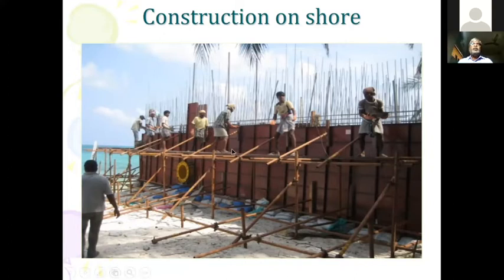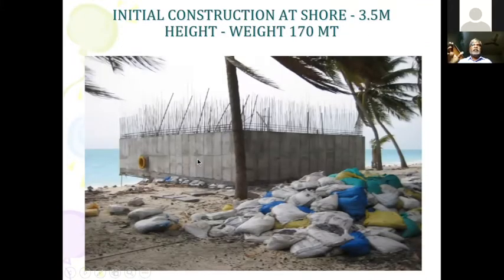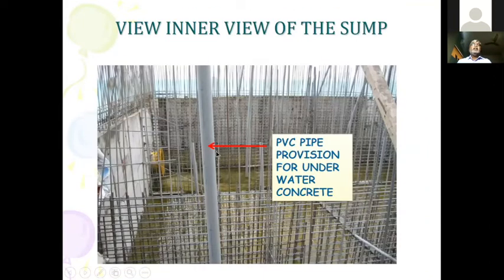So we have gone up to 3.5 meter, and you can find all these inserts have been provided for the pipelines to get connected. As I said, it's about 3.5 meter, although 200 tonner is a buoyancy which can float. We have taken about 170 tonner as the weight of this at this particular point. And as I explained already, although we are going to make the seabed a fairly level surface, we will not be able to make it pakka.